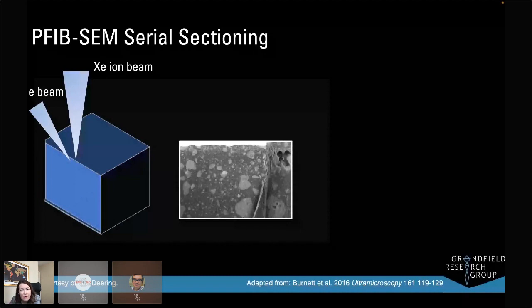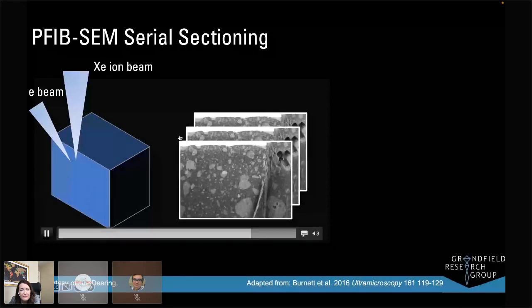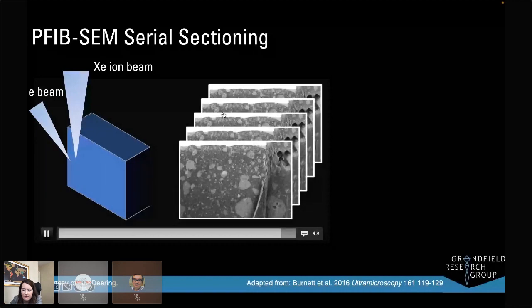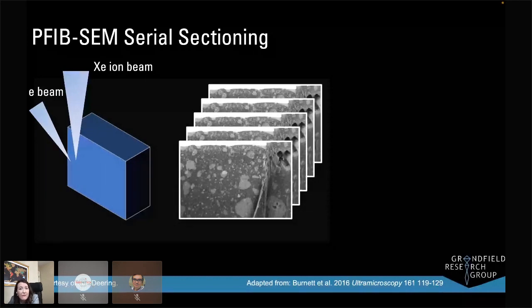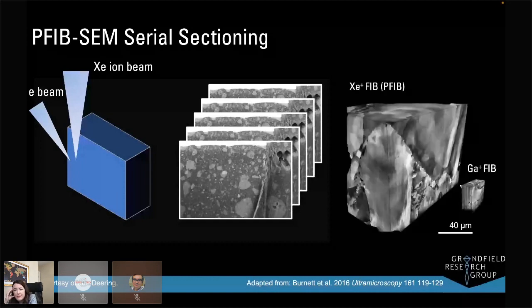We repeat this over and over—you can see the sequential milling and imaging—and then we stack up these images together and create a 3D reconstruction. The advantage of using a plasma FIB, or xenon-based FIB, is that we can access much larger volumes than using a smaller gallium ion beam. Here's an example from other work where you can see a comparison between the two volumes you can access with these two tools.